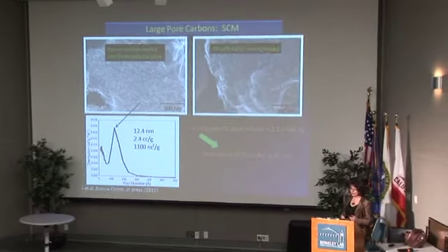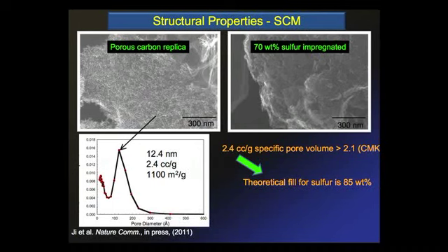And the other question is how to get cheap carbons to do this. So we've made porous carbon replicas from a colloidal silica. This is just Ludox, nothing fancy, size-controlled Ludox. These have pore dimensions in the vicinity of about 12 nanometers with a suitably high pore volume and surface area, higher than that of CMK3, such that we can now get 85% sulfur into these materials. And this just shows the sulfur-filled material. Now, we don't actually go to that fill ratio because it doesn't allow us the space for access, but we can get pretty close to that.